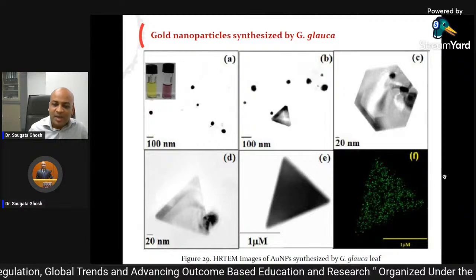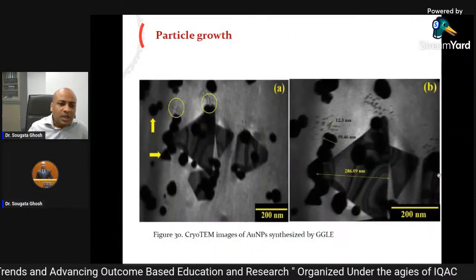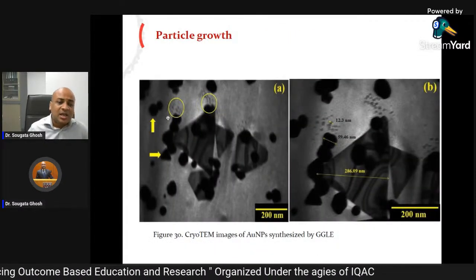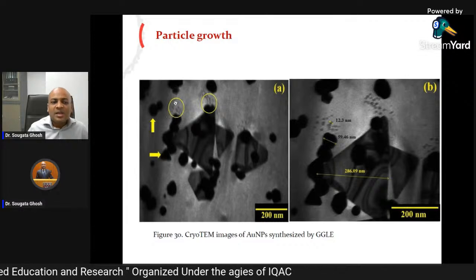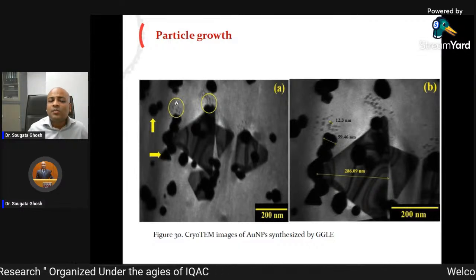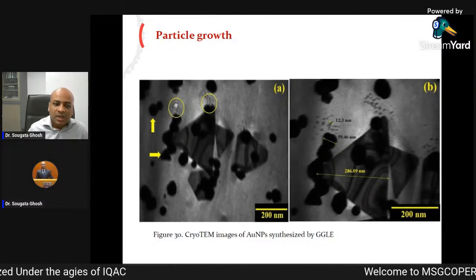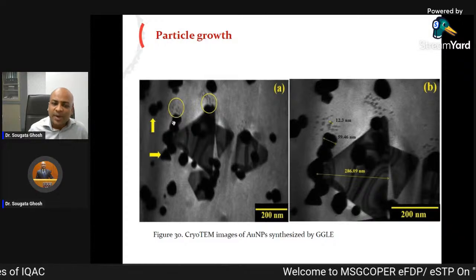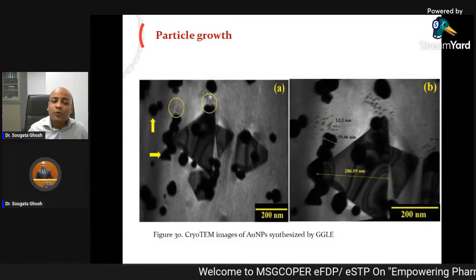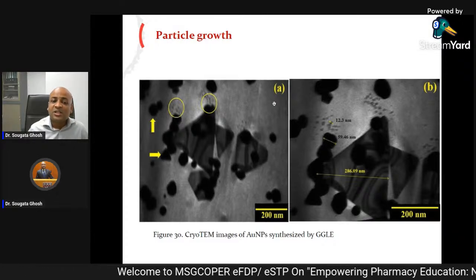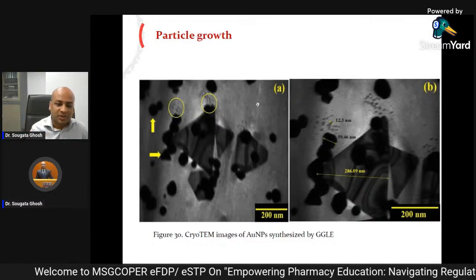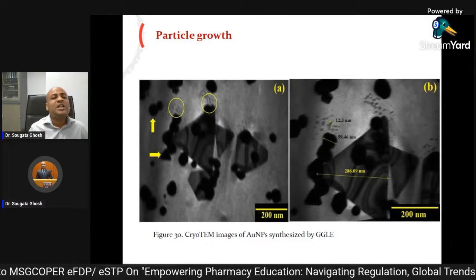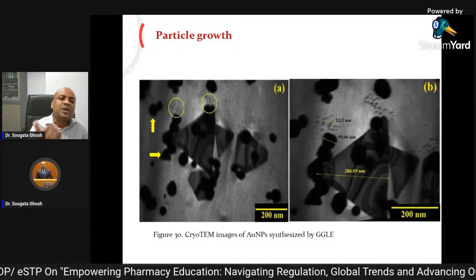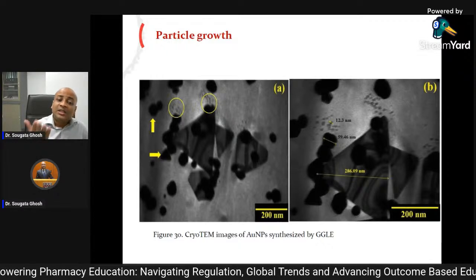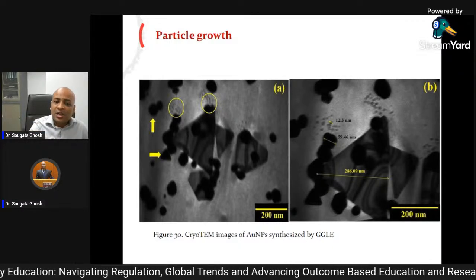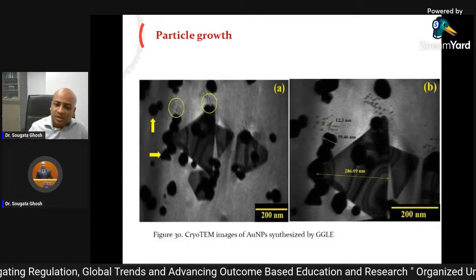This is elemental mapping. Here, very interestingly, an important observation we found was that initially very small particles were coming together to form bigger particles, and they were coming together to form triangles. This is called the Ostwald ripening process. It is theoretically explained, but it is very rare to see in practical application. But the G. glauca leaf actually showed this to us.